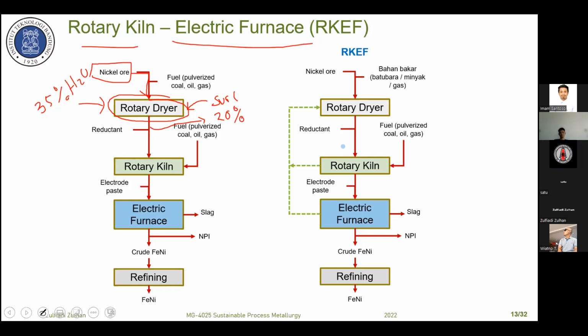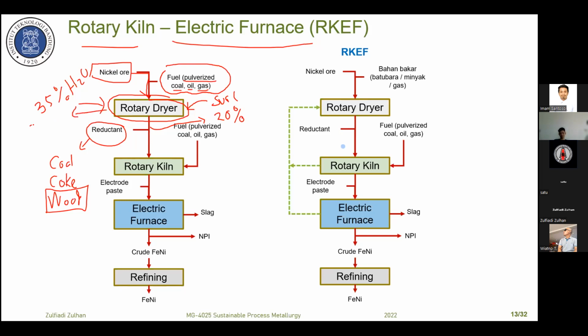And then this dry ore is mixed with reductant. The reductant could be coal, coke or semi-coke. In other countries it could be wood chip, and later on we can also use wood chip, also biomass, as reductant for the rotary kiln. The energy source for drying comes from burning pulverized coal, oil or natural gas. The temperature here is around 300 to 400 Celsius degrees, and the water content in the product is around 20%.